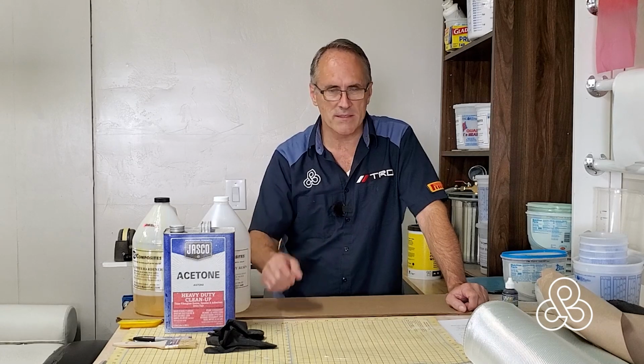As I mentioned foam, you might know that epoxy is probably the product you're going to go to if you have to put a fiberglass layer on some foam, either on a plug or on a product itself that you're trying to create, as epoxy is very good at not attacking foams chemically. Now, if you try to put polyester or vinyl ester onto some styrene foam, packing foam, or the kind that you find a cooler made out of, it will pretty rapidly dissolve it away into a gooey mess, whereas epoxy will not do that. And so if you're ever going to use, like I said, foam for building anything, you're going to be going to epoxy anyway.